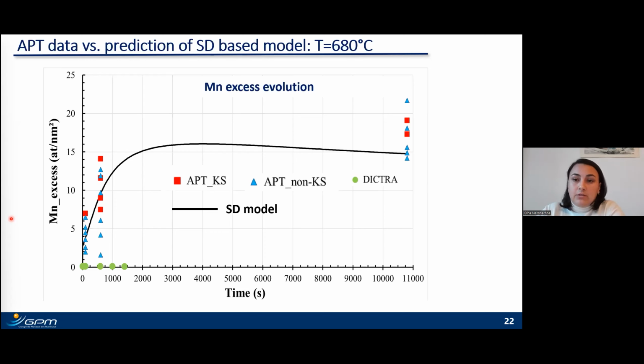But based on the presented results, we see that solute drag provides a much better qualitative description of the experimentally observed profile at the investigated conditions. And so then the model used the assumption of local equilibrium. Therefore, solute drag-based models are a very promising direction for the description of the austenite to ferrite phase transformation that was opened thanks to the unique data obtained by atom probe.